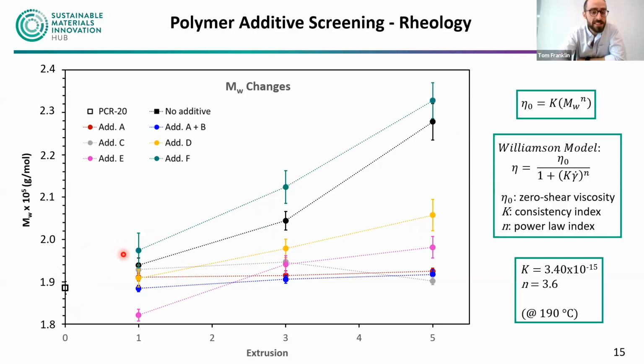And in particular, this green one here almost mirrors our behaviour when we don't have additives. We know just from this plot, without additives, we're getting branching, we're getting changes to that molecular structure. So we would expect to have a knock-on impact on our mechanical properties. Some of our additives perform really well, no changes. Others not quite so well, and others really quite poorly.